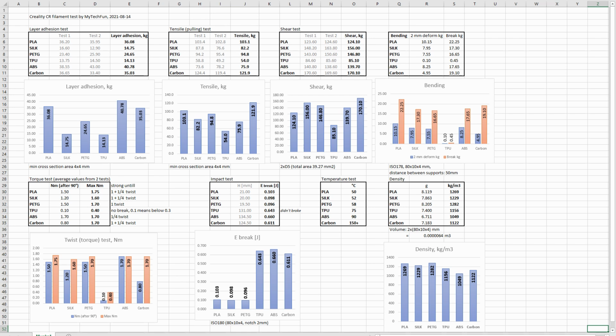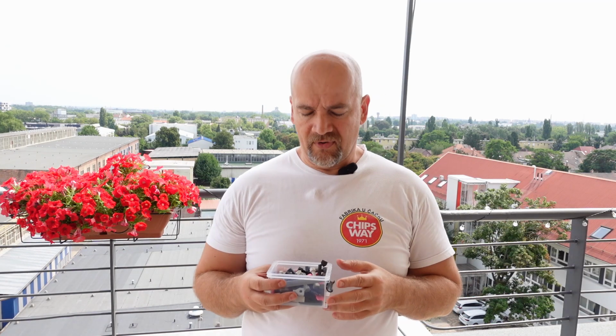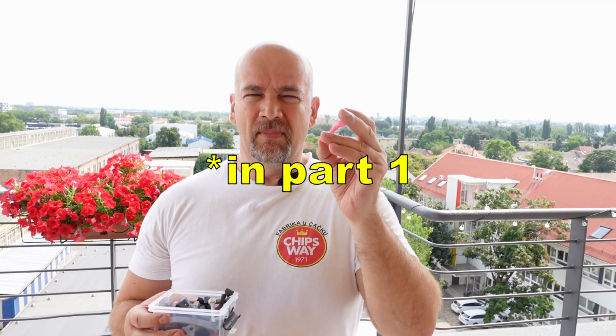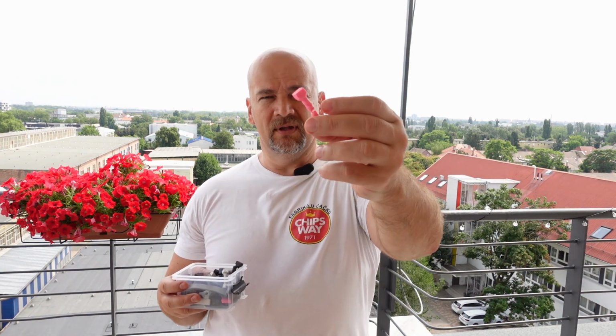And for the moment I will show you all results in one place. And now our final thoughts. Let's start with the PLA. It's not so easily printable like regular PLA. You saw I had some problems with overhang, but on mechanical test it performed quite good. Even in that impact test, PLA is usually brittle, but you saw in impact test or even in this twist test how many rotations I could make. So from mechanical aspect it's not bad.